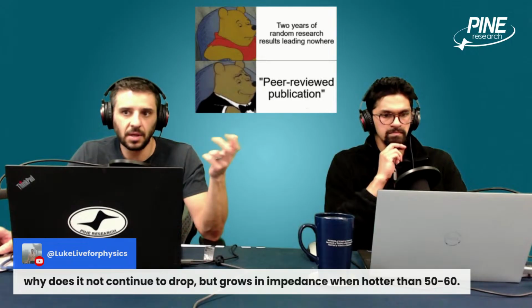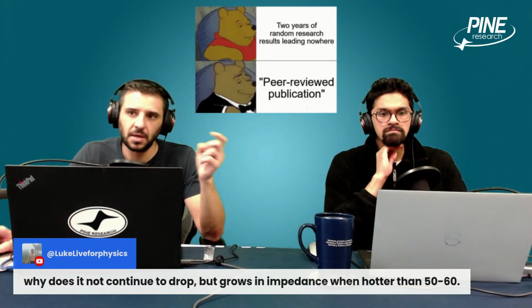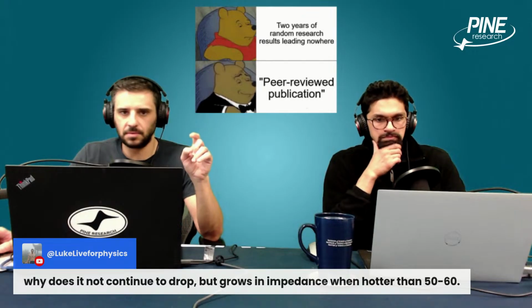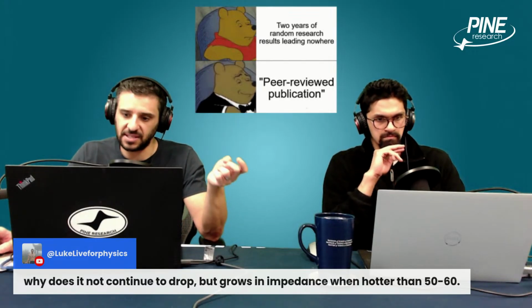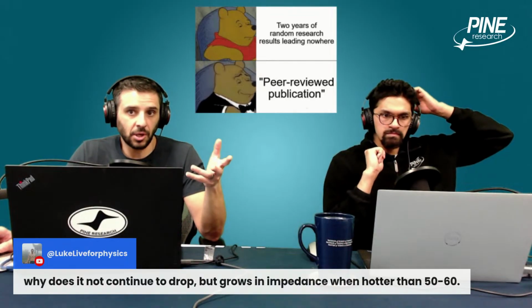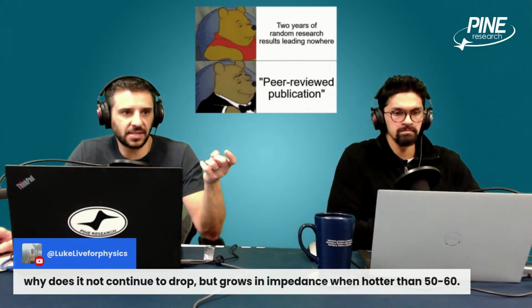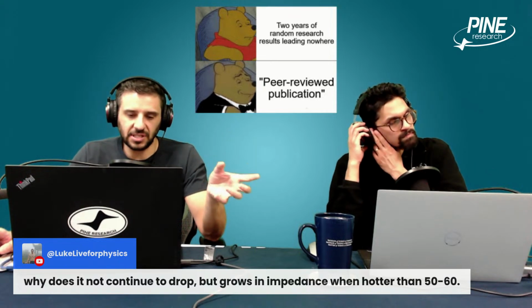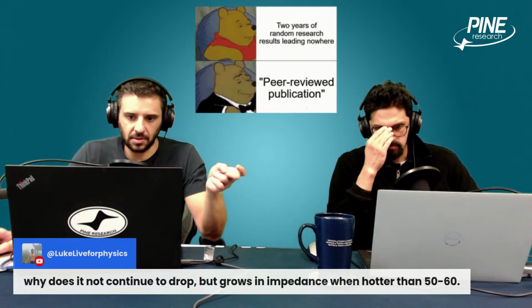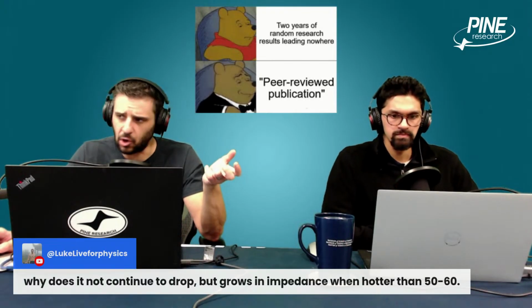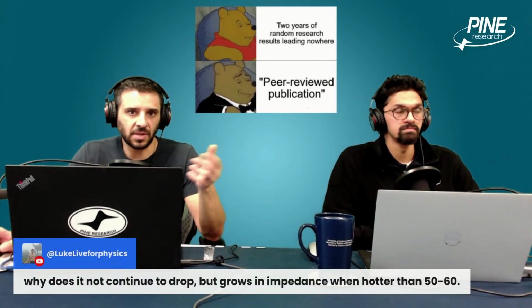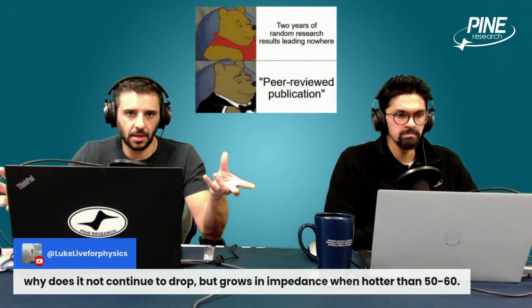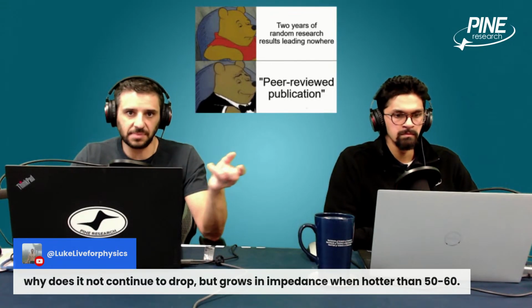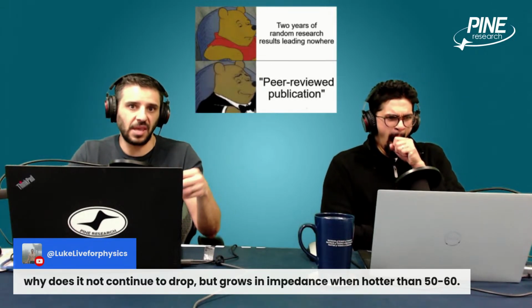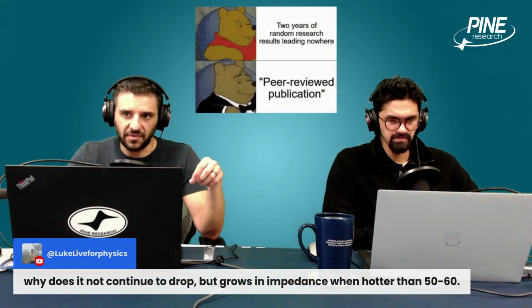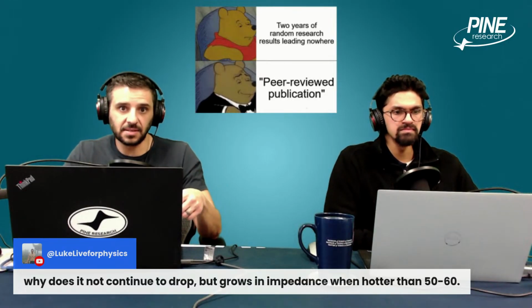And then you could theorize why. Look at the different physical properties of NCM or NCA. You might be able to see that in some cases, a different phase will form at different temperatures. With the cathode, NCM is nickel, cobalt, manganese oxide, basically. So you have three different transition metals along with lithium and oxygen, so there's a bunch of oxidation states. Maybe an oxidation state changed. Maybe at certain temperatures, some of the manganese leaves the lattice.